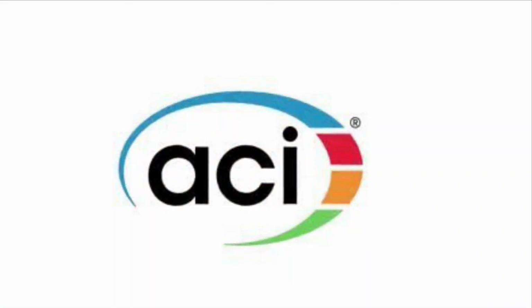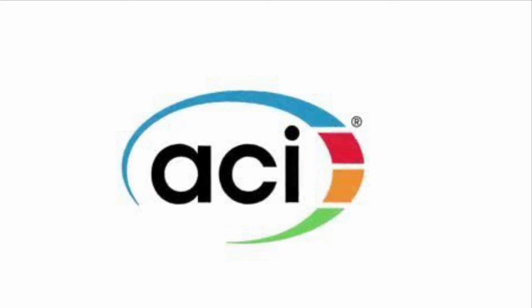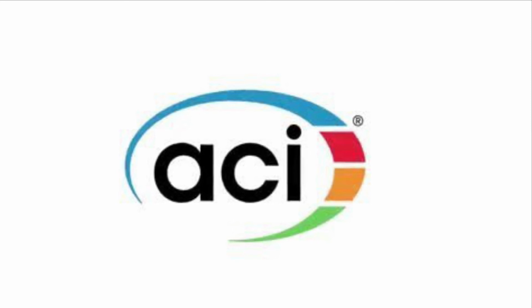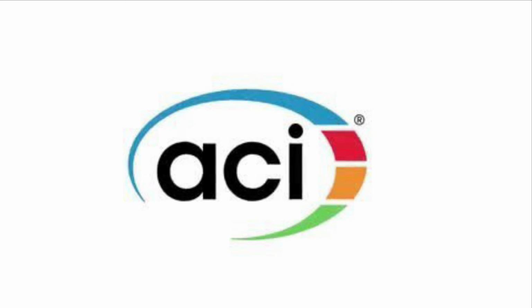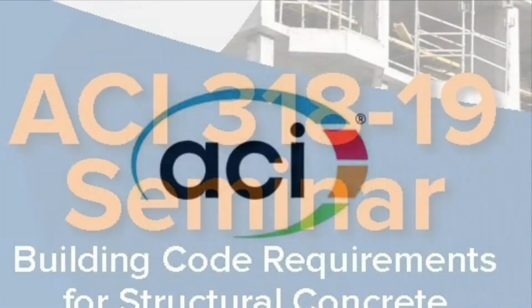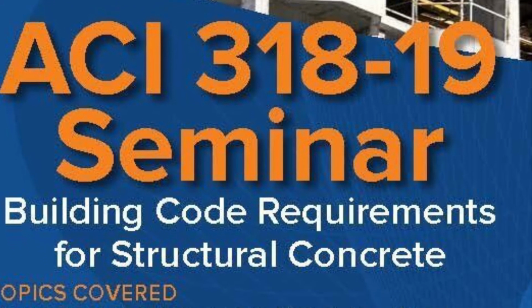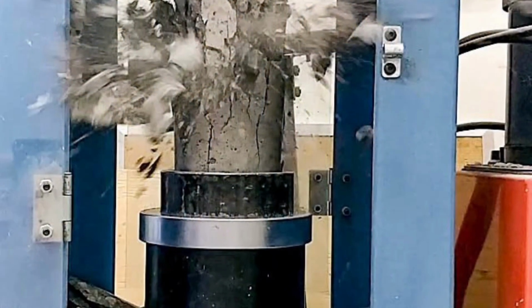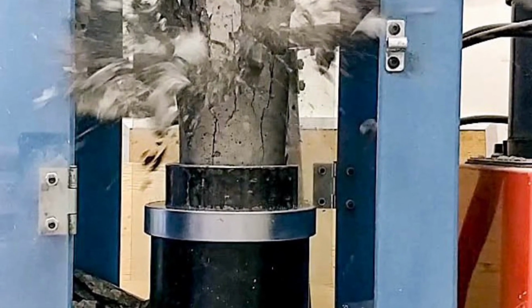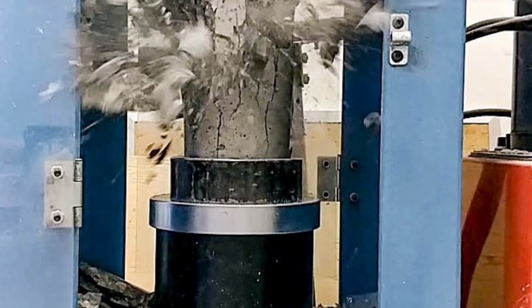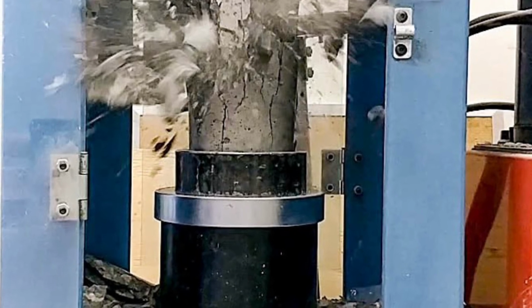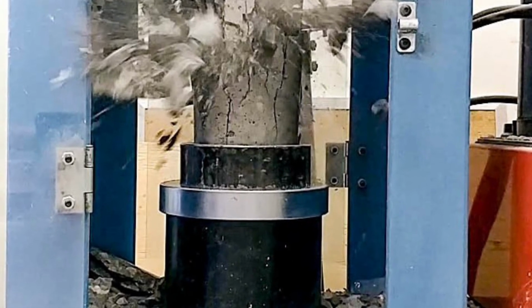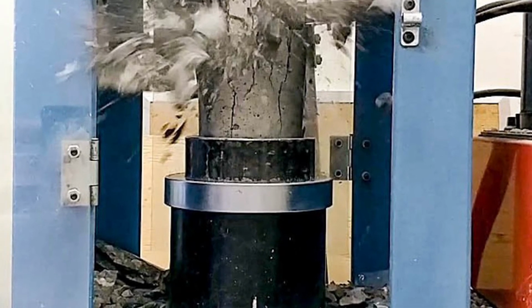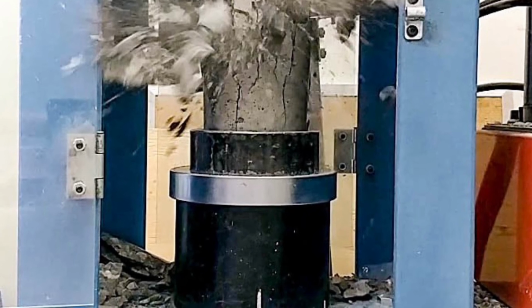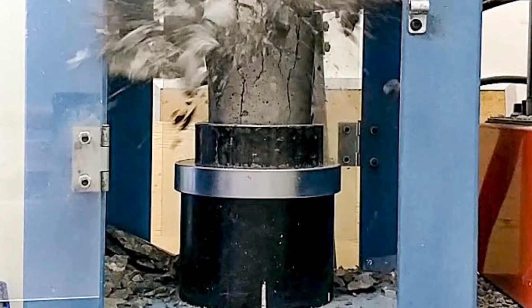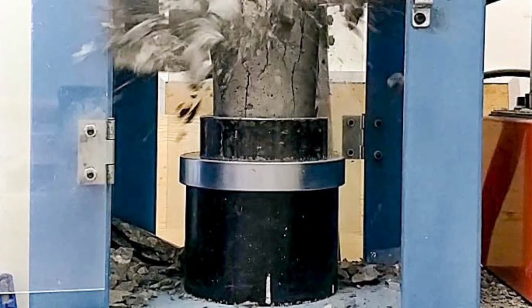The American Concrete Institute is a leading authority in research worldwide for development, distribution, and adoption of consensus based standards, technical resources, education, and proven expertise for individuals and organizations involved in concrete design, construction, and materials. The American Concrete Institute has requirements for structural concrete and strength. These codes can be found in ACI 318-19. These state that the average strength of three consecutive test cylinders should be greater than or equal to the design strength needed for the foundations. For strengths of 35 megapascals or less, the compressive strength should not be less than the design strength by more than 3.5 megapascals. If the strength is greater than 35 megapascals, it should not be less than the design strength by more than 10%, otherwise resulting in a failure.